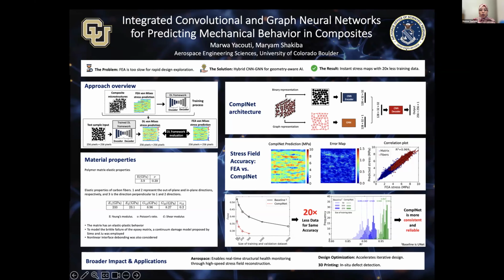In our results, we show that CompiNet accurately reconstructs full field stress maps, reduces the amount of required training data by 20 times, and achieves up to 150 times speed up compared to traditional finite element simulations. The result is a model that delivers full field stress maps in seconds, giving designers instant visibility into stress hotspots and likely failure zones. That means they can screen millions of layouts overnight and move only the most promising designs to costly experimental testing. The real power of CompiNet isn't just making simulations faster, it changes what's possible for engineering.